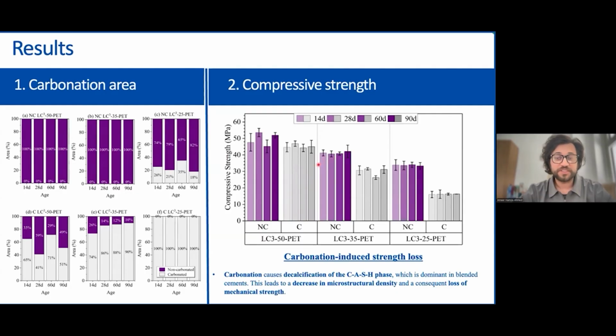That makes sense because in the blended cements, such as LC3, the hydration and the pozzolanic reaction lead to formation of C-S-H phases, which are the most dominant phases in the blended cements. And when CO2 interacts with these C-S-H phases, it basically decalcifies and destroys this dense network, causing an increase in the local porosity wherever the CO2 interacts with these C-S-H phases, and the strength can drop.